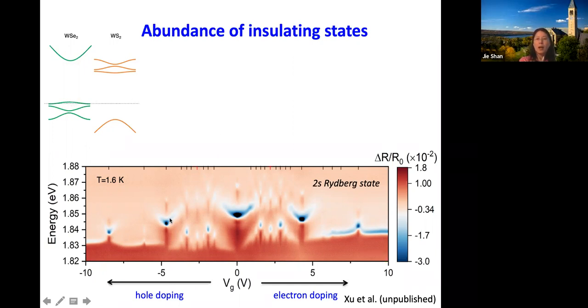So you see the change of those peaks, or candle-like objects. This tells us the 2s exciton energy. For example, a higher 2s energy means the material is more insulating, right? And the darker the blue color, the bigger the oscillator strength. The peak at voltage equals 0 corresponds to the Fermi level in the middle of the gap. This is the largest band gap of the system, and this is a very good insulator.